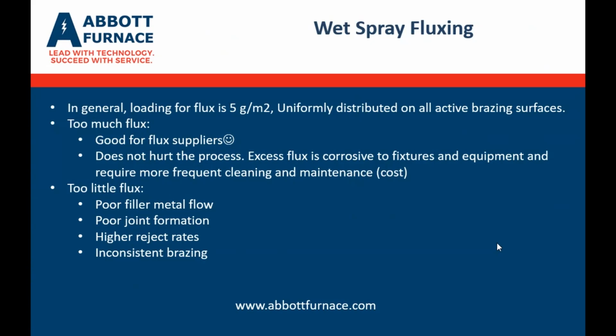corrosive to the fixtures, to the equipment, and will require much more frequent cleaning and maintenance, which is downtime and cost. Too little flux, on the other hand, will give you poor filler metal flow, poor joint formation, bad quality joints, higher reject rates, and inconsistent brazing.